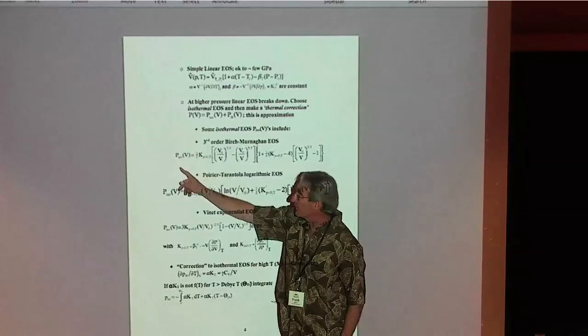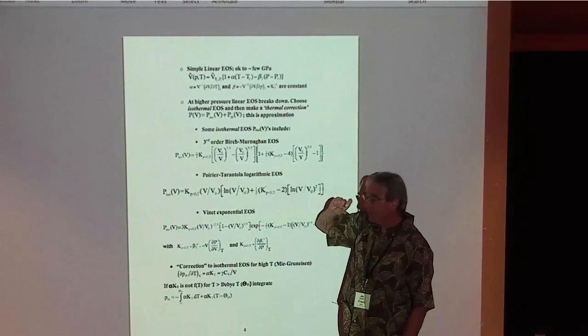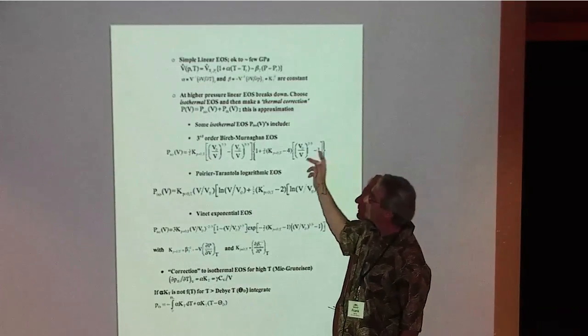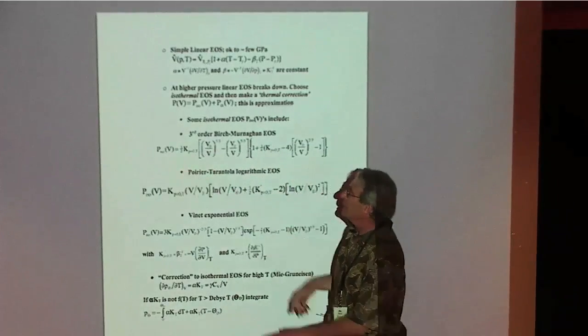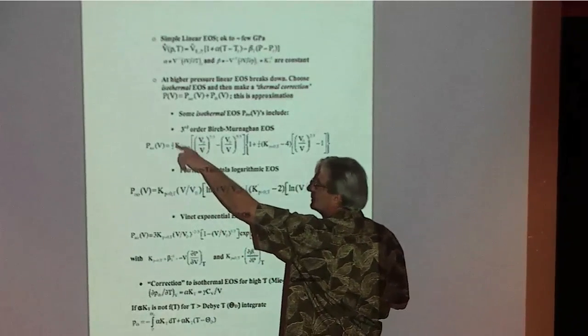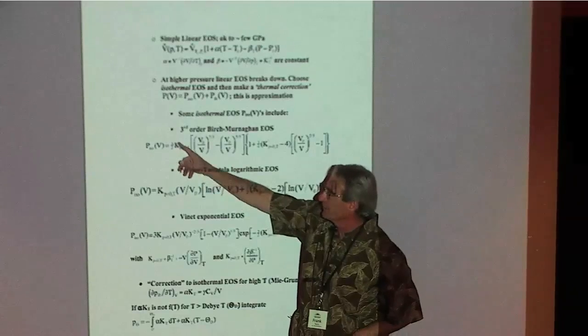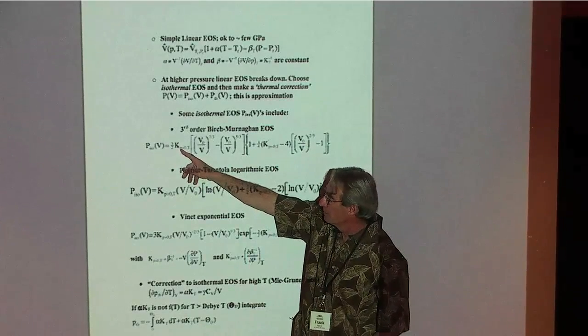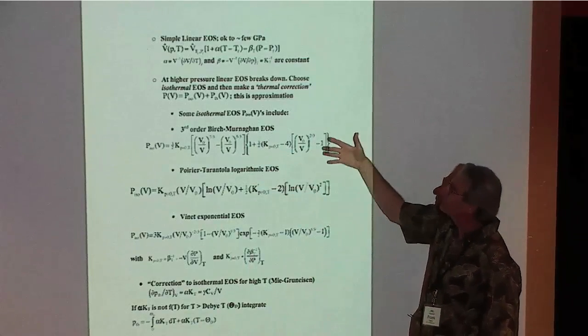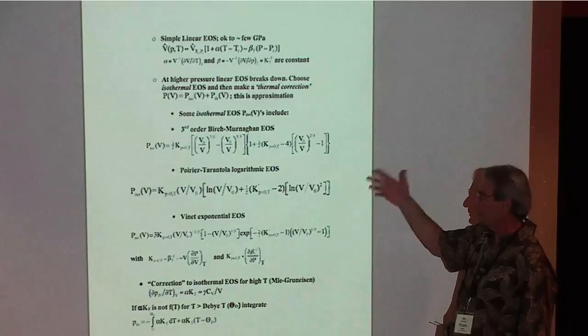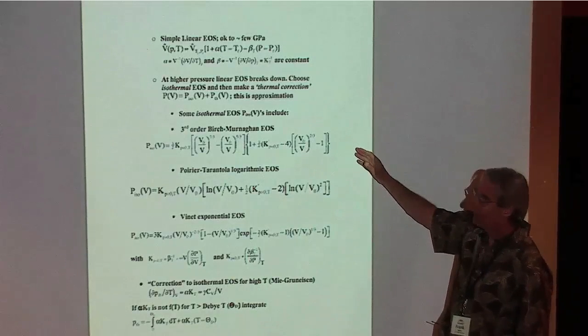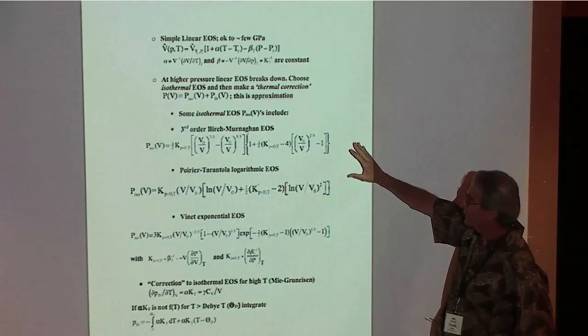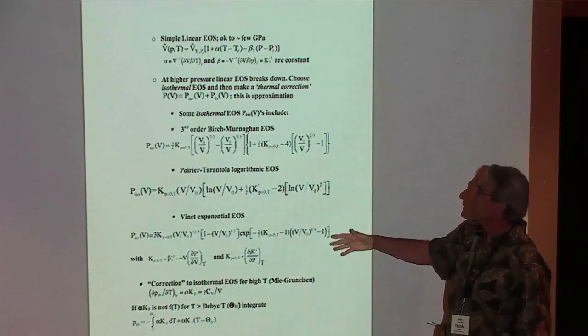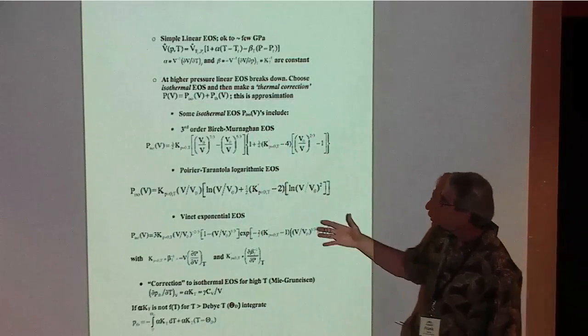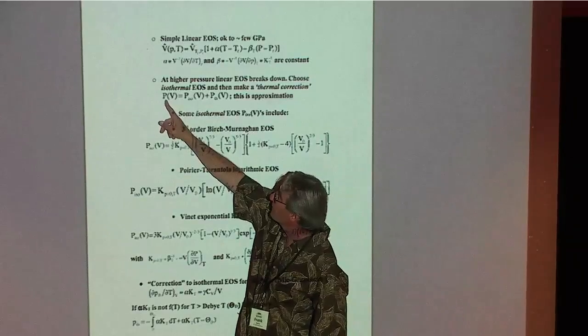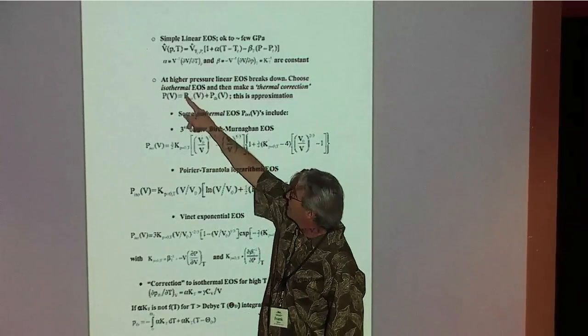This is just a relationship between the pressure and the volume, and this is done along an isotherm. So at some temperature, this is the relationship between volume of the material and pressure. It involves the bulk modulus, or 1 over beta, the isothermal bulk modulus, and its derivative. We have these different flavors, these different relationships, and people argue about these and propose more. There must be tens of these. I'm not an aficionado of these; probably someone like Quentin would be. But we have all these different ways of doing it, the Vinet, and so forth. And so that gives us the isothermal part, because what we're after is a relationship between pressure and volume.